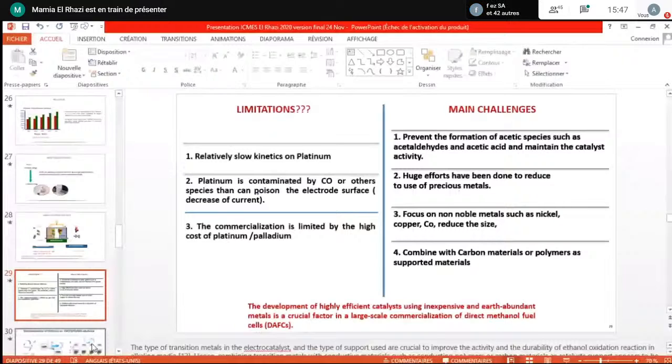The first example I will give you here is about electrooxidation of methanol on carbon nanofiber, phenylenediamine and copper. Sorry, it's not nickel here, but a copper electrode. We have done the study with nickel and copper, and here I present the work done with copper. We explored a new catalyst material based on copper dendrites supported on carbon nanofiber polymer hybrid nanocomposite for the methanol oxidation reaction.